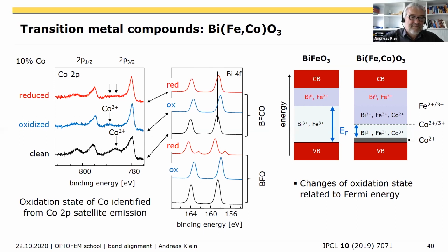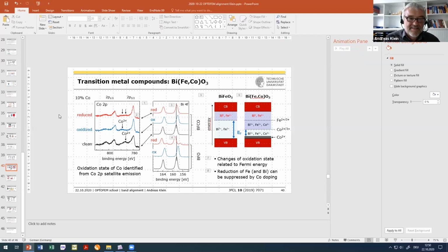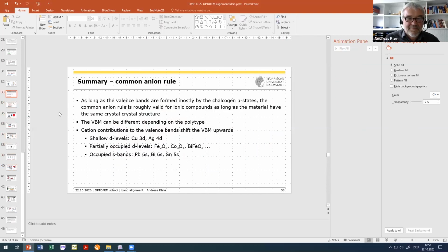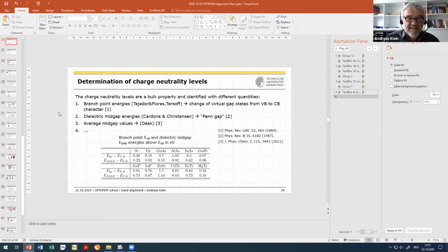Okay. I have a question myself regarding XPS and defects. Some people try to rely on XPS to identify oxygen defects, oxygen vacancies. What are your thoughts on that? To be frank, the literature is full of nonsense regarding oxygen vacancies and XPS measurements. If you look at the oxygen 1s peak, in most cases it has a shoulder at high binding energy.